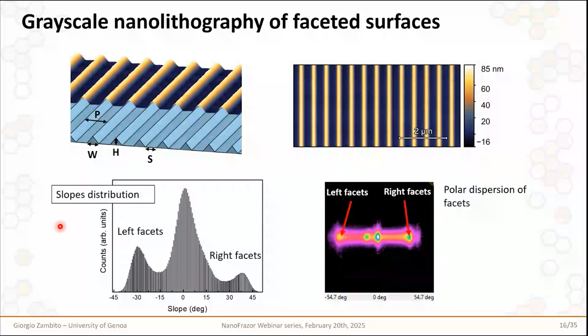And also by the slopes distribution, which is basically a histogram of the first derivative of the topography image that I show here, we see three main peaks representing the flat areas, also reproduced via NanoFrazor lithography, but also the presence of two peaks representing the left and right facets. And this is also observed by the polar dispersion of the facets, where we see the presence of these peaks, again relatable to the presence of left and right facets, and also we see the fact that they are distributed horizontally, which means that we actually have the tilting of the facets along the x-axis.